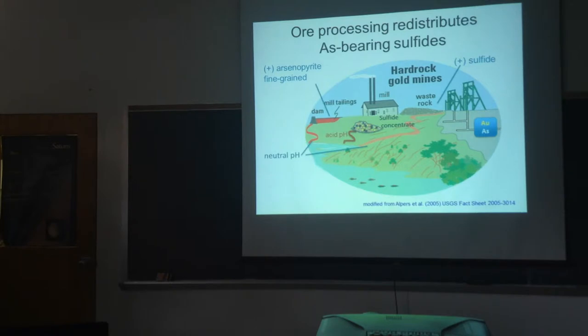Sometimes there'll be a concentrate, again, knowing that some of the gold will be associated with sulfide minerals such as galena and pyrite. The miners would create a concentrate of the sulfides, but maybe they never got around to processing it or sending it to either a smelter or a roaster. You can't just put a sulfide concentrate in with cyanide, which is the gold extraction method of choice starting around 1910 or 20, because the cyanide will interact with the sulfide. So you need to oxidize those sulfides first. So sometimes they left these concentrates lying around because they didn't get around to processing or pre-processing them prior